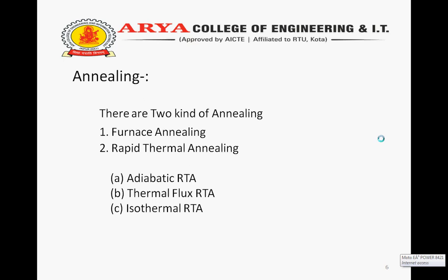Rapid thermal annealing is a term that covers various methods of heating wafers for periods from 100 seconds to nanoseconds, allowing repair of damage with minimum diffusion. RTA can be divided into three classes. First is adiabatic RTA. In adiabatic RTA, the heating time is short, less than 10 to the power minus 7 seconds, so that only a thin surface film is affected. A high energy laser pulse is used to melt the surface to a depth less than 1 micrometer.